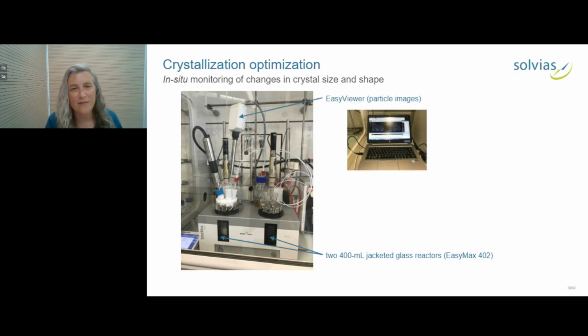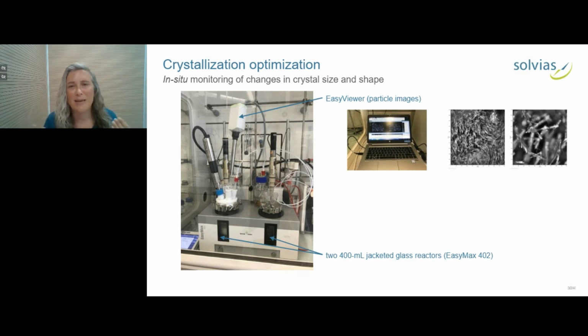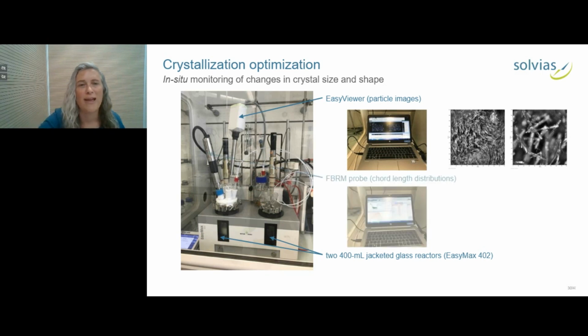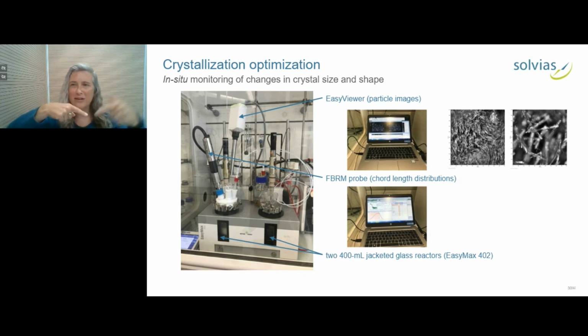and one of them is the EasyViewer from Mettler Toledo, and that actually looks inside the system and records images in situ. So during your whole crystallization process, you can actually look in the system and see what happens. You can see changes in size and shape or agglomeration or breakage. There's also the focused beam reflectance measurement probe. So this is a system for measuring chord length distributions. What happens is you have a laser that rotates, and as the path of the laser intersects with the path of the particle, it will reflect the light back, and the length of the pulse that results is basically one dimension of the particle.